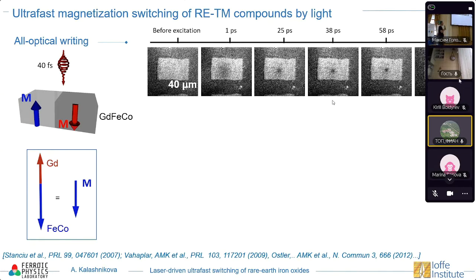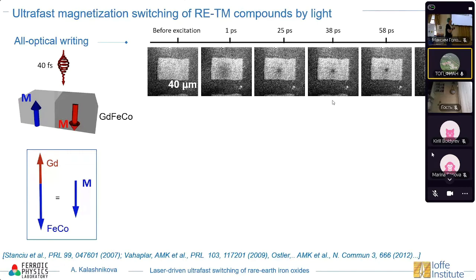But in principle, maybe the most striking demonstration of how rare earth transition metal compounds can help us switch magnetization is so-called all-optical magnetization recording or magnetization switching, which was found in rare earth transition metal compounds like gadolinium, iron, cobalt. These are metallic ferrimagnets. The magnetic structure is shown here. And this is one of the main experiments. Basically, what is shown here are magneto-optical images which show the orientation of magnetization, taken with very high temporal resolution after excitation of this material with a 40 femtosecond laser pulse. First we have a white area which shows that magnetization was, for example, pointing up. And then after several picoseconds, we see some gray area. And then already after 50 or even 30 picoseconds, we see a black domain, which shows that magnetization switched. And it happened without any external magnetic field. So for a while, it was really a mystery what was going on.